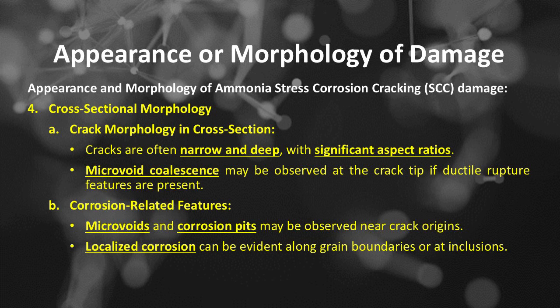Appearance and morphology of ammonia stress corrosion cracking damage. Number 4 is cross-sectional morphology, includes, number A, crack morphology in cross-section. Cracks are often narrow and deep, with significant aspect ratios. Microvoid coalescence may be observed at the crack tip if ductile rupture features are present. Number B is corrosion-related features. Microvoids and corrosion pits may be observed near crack origins. Localized corrosion can be evident along grain boundaries or at inclusions.